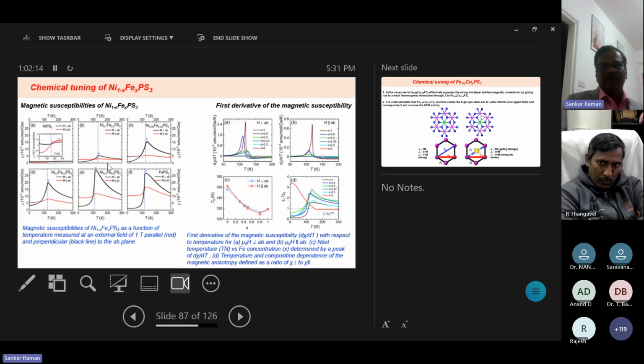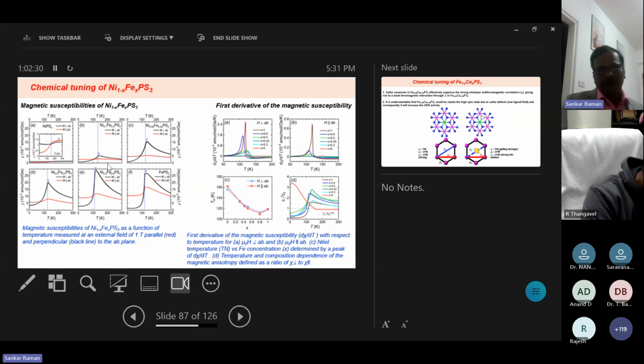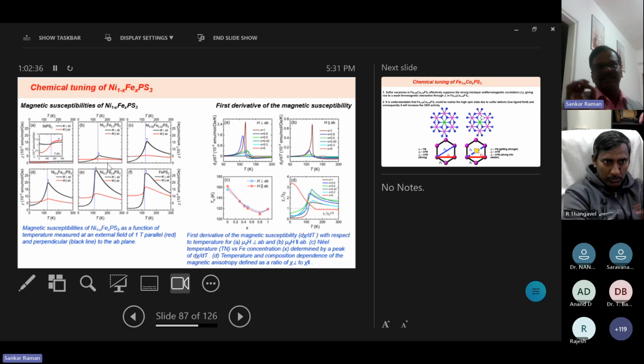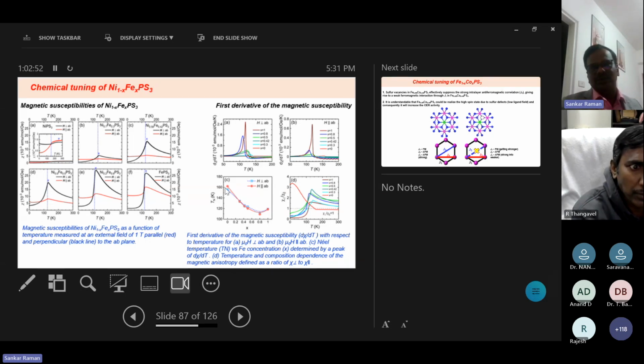And also we doped with magnetic material, along this nickel and iron phosphate. We changed the transition and also changed the in-plane and out-of-plane antiferromagnetic transition also. In this slide, you can clearly see initially is a broad maxima. After that, we doped a small amount of iron on the nickel side. You can clearly see the 1D to 2D magnetic transition, the broad maxima has appeared, and also you can clearly see the sharp transition. With respect to the composition, you can increase the TC value from 162 up to 180.